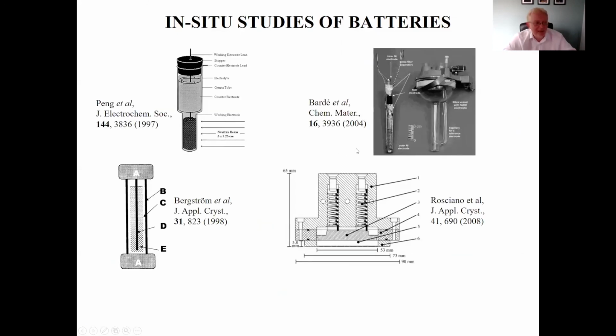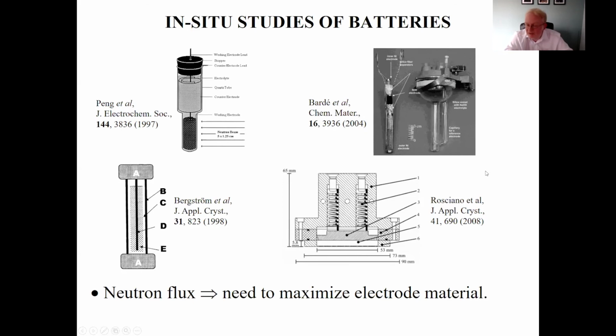And of course we study batteries. Now batteries are quite a tricky thing to study because you need to maintain the electrochemical purpose of the battery material itself. There's no point in building a battery cell that is not electrochemically interesting. And you also need to maximize the amount of electrode material that you put in the beam, because we need quite a lot of material in the neutron beam to get decent neutron data.